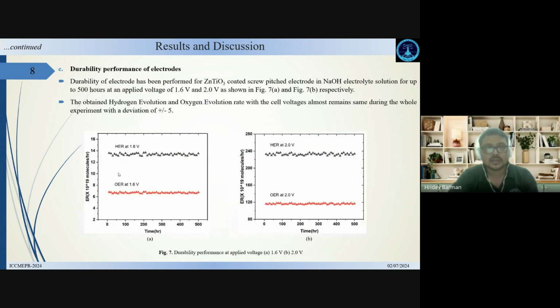Yes. So after that, we have to confirm the durability of the electrode material. For that, we have done this experiment continuously for up to 500 hours at an applied voltage of 1.6 volt, and I have taken only 1.6 volt and 2 volt as shown in figure 7a and b. So here we can see that the hydrogen and oxygen evolution rate with different cell voltages almost remains the same during the whole experiment, with a deviation of ±5.